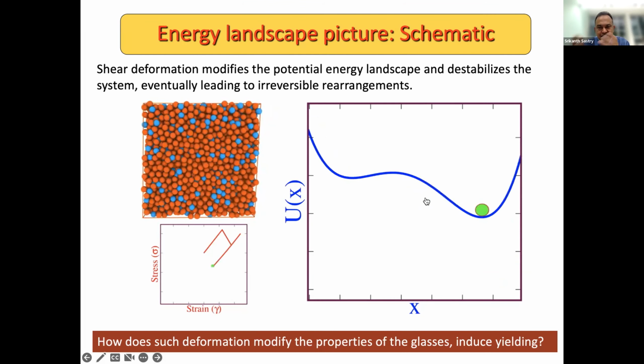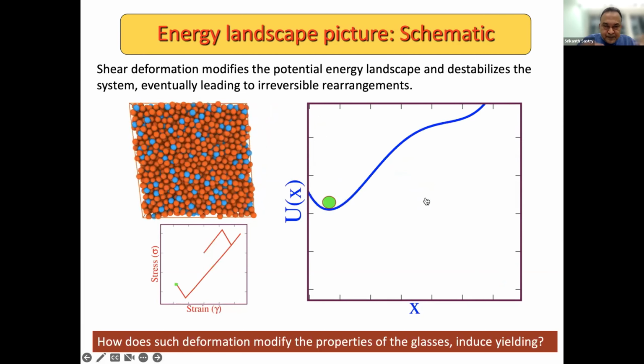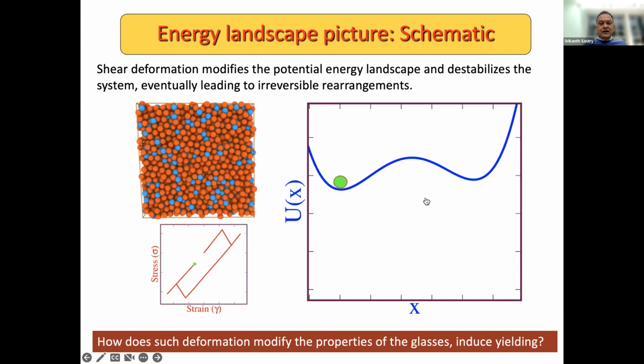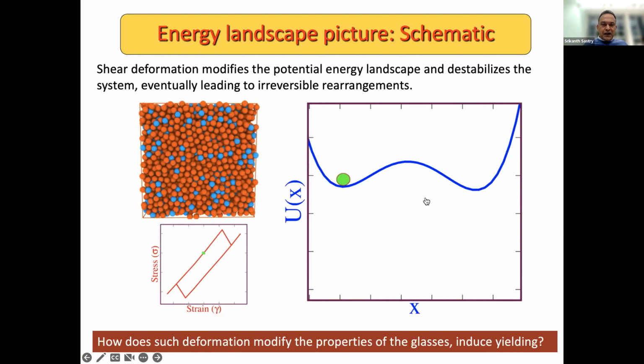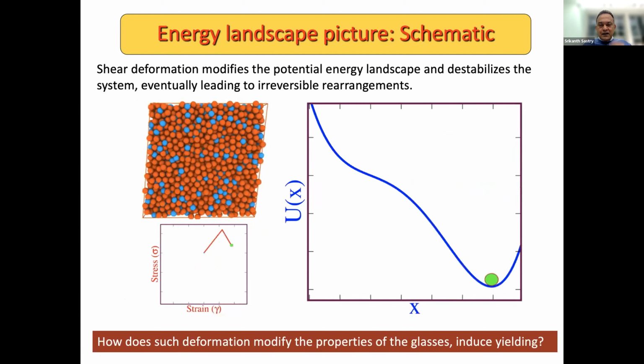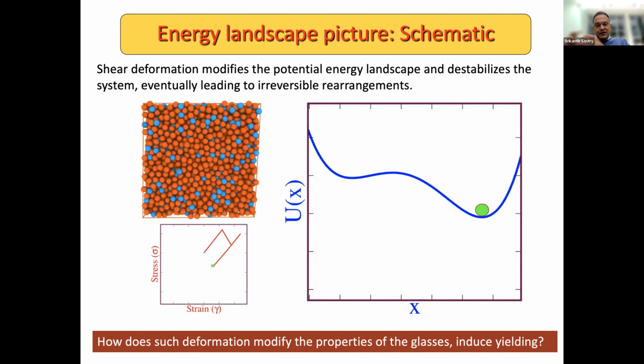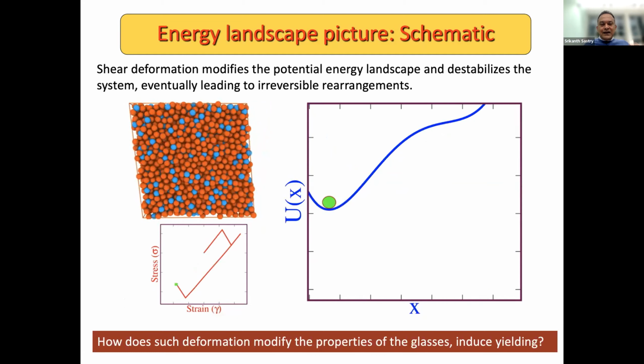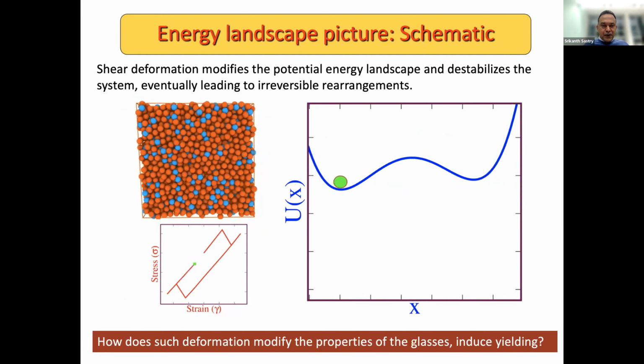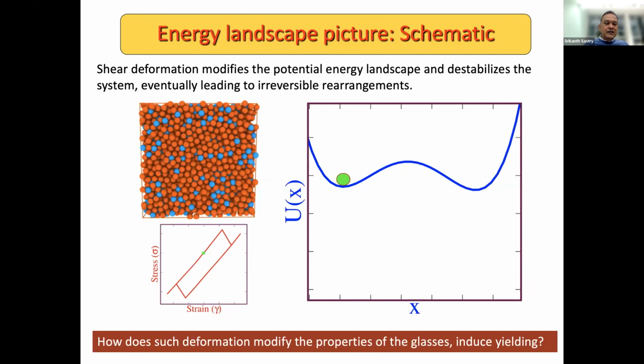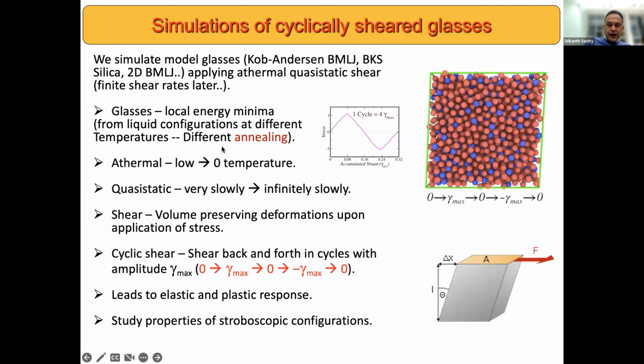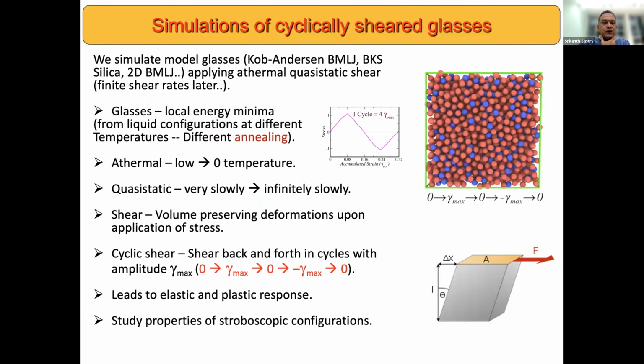So if you imagine that in this simple cartoon, your system is capable of being in one of two minima in a bistable system. Your shear deformation tilts this landscape so that the initial minimum that you may be in becomes unstable, and you go over to the other minimum, which will eventually become unstable, but not at the same point as when the first minimum became unstable. And this leads to a situation where the state of the system at a given strain value depends on the history.